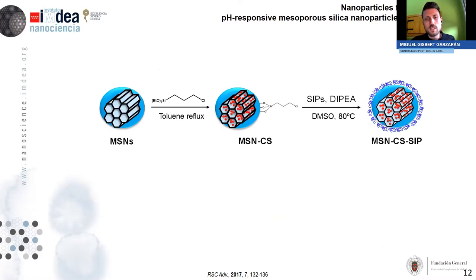Okay, so for the functionalization of the nanoparticles, because the silica nanoparticles present many silanol groups on the surface, a very common approach to functionalize silica is to use alkoxy silanes bearing some kind of functional moiety. For instance, in this case, we have a chlorine group, but we can have an amino group, a carboxylic acid, many different things. So in this case, we used this alkoxy silane, and then we added the self-immolative polymers, which are referred to as SIPs many times throughout the talk. So basically, we added the alcohol of the self-immolative polymers to this alkoxy silane, and then we got our SIP-coated mesoporous silica nanoparticles.